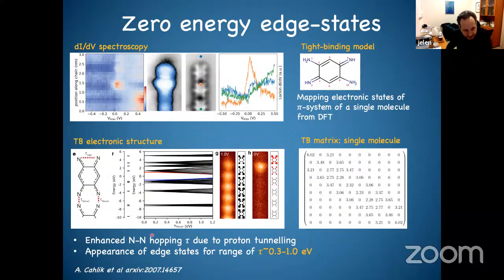And now when you start to play with this, you will start to see that at certain conditions, for some reasonable value like hopping, which is still lower than the intramolecular hopping but in the range of 0.3 to 1 eV, the edge states start to appear here. So maybe what we can say is that the electronic states which appear here are due to this proton tunneling, which is dragging the electron itself. It's enhancing the effective electronic hopping between these two molecular units, and this gives rise to new electronic states.